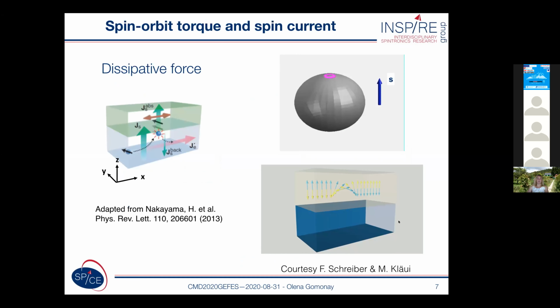So we start with the dissipative force, because in the experiments, we usually apply current to the platinum electrode, as shown in the left panel. And due to the spin Hall effect, this current can create a spin flux, a vertical spin flux in this figure, which is absorbed by the antiferromagnetic layer. So in this system, electrical current creates spin orbit torques. And what can be the consequence of these torques?